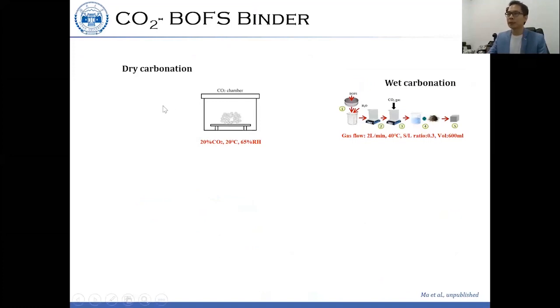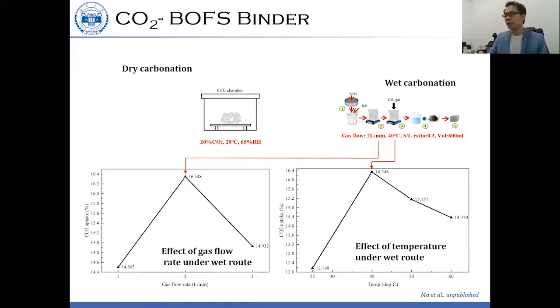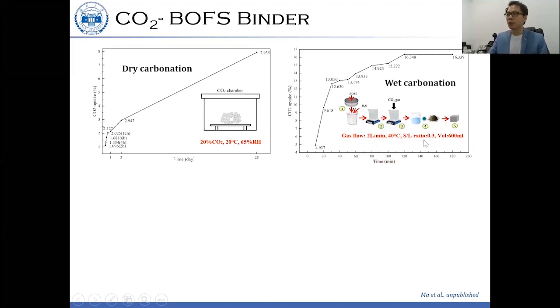We have compared dry carbonation and wet carbonation for the BOFS binder. The dry carbonation parameters are similar to what I mentioned in the previous slide. We also tested the carbonation parameters in terms of gas flow, temperature, and solid to liquid ratio, and found that the optimal values are 2 liters per minute, a temperature of 40, and a solid to liquid ratio of 0.3. We measure the reactivity of the material by measuring the CO2 uptake.